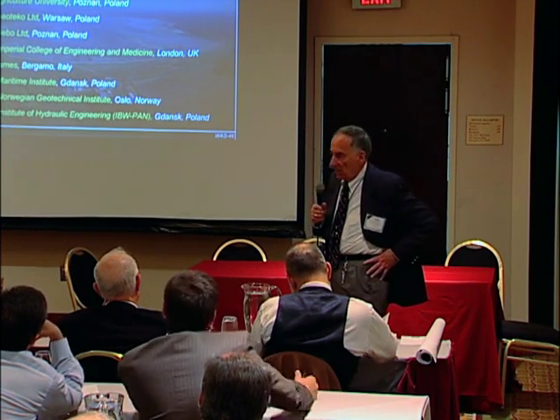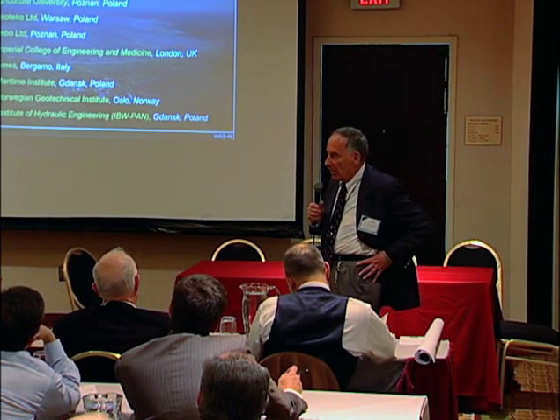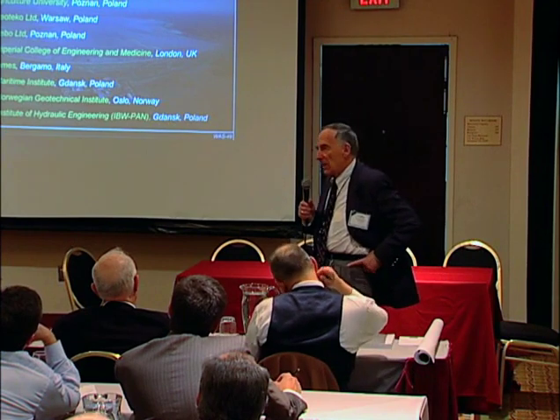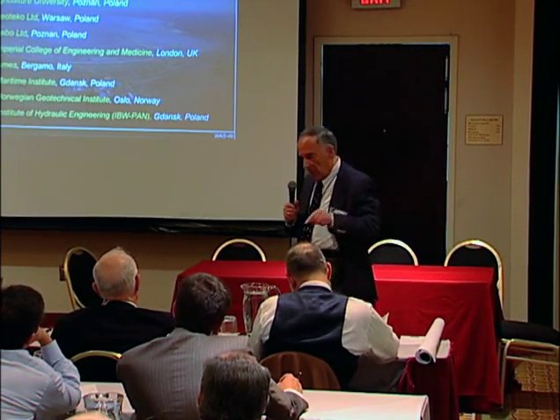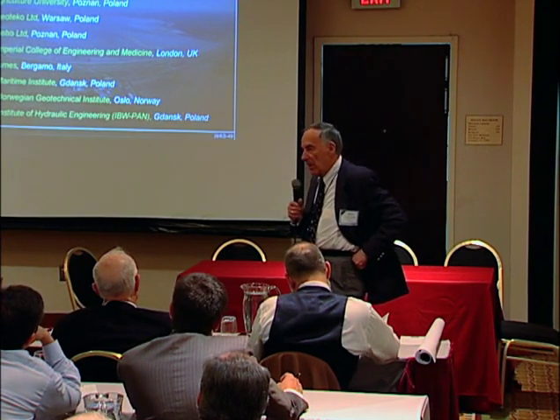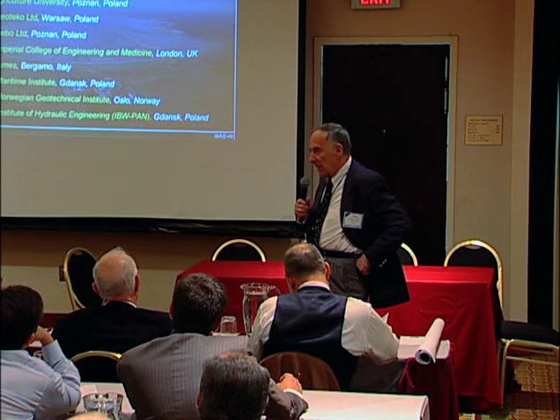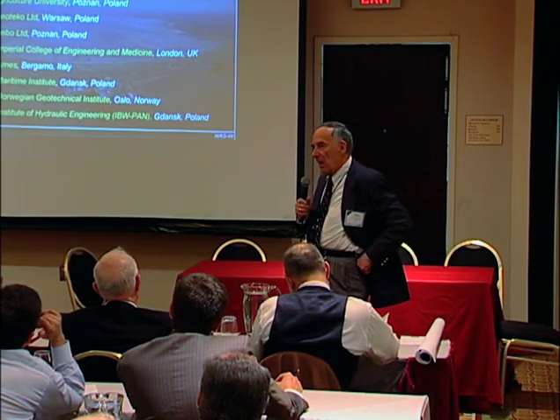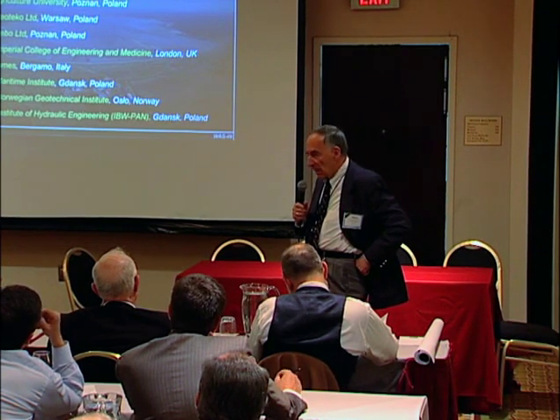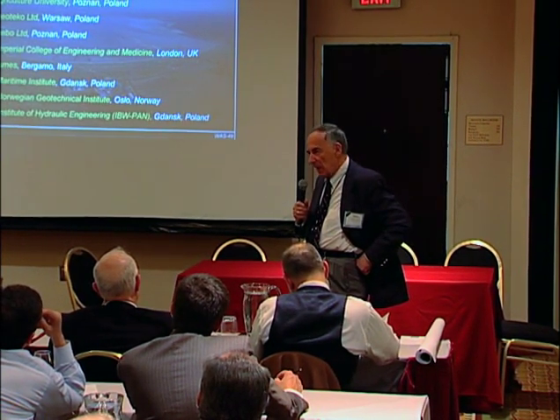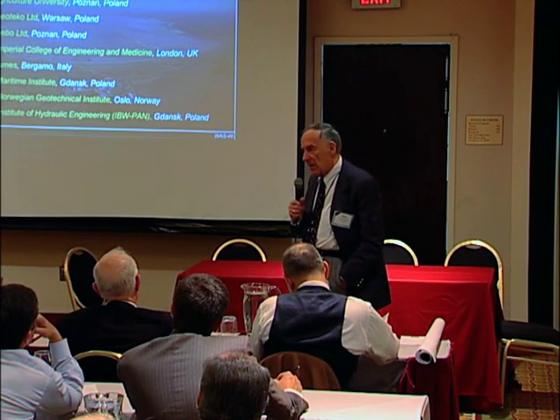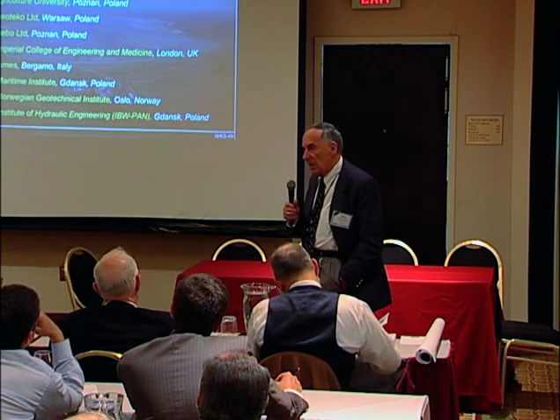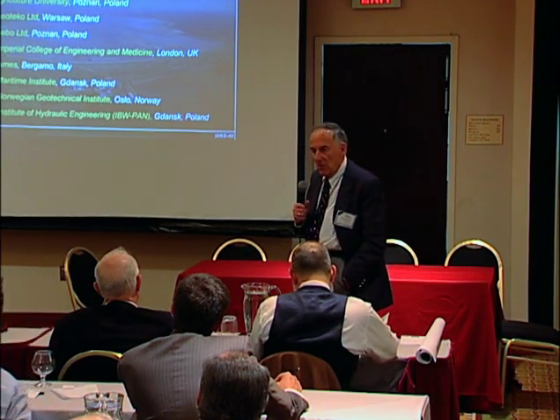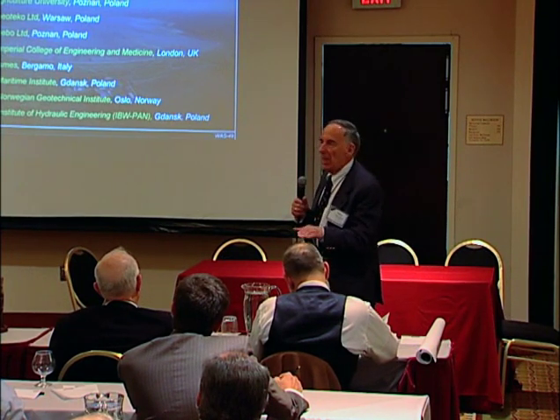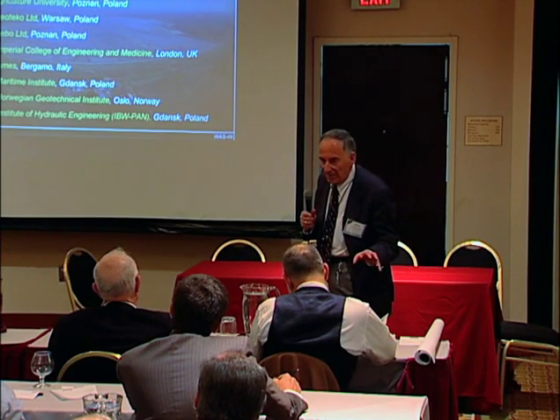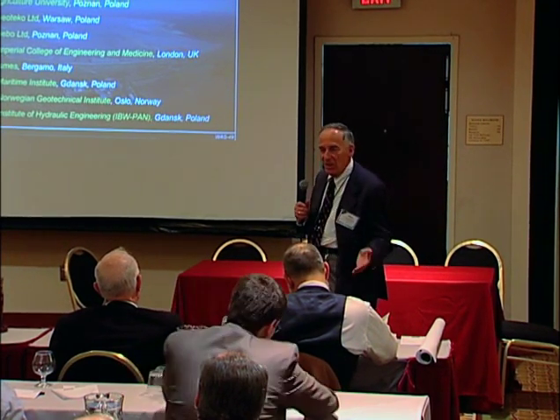On the other hand, we have some indication from the shear wave velocity and from some general information that tailings, indeed deeper tailings, are subject to aging. And in fact, our next step will be to retrieve the undisturbed samples and to investigate in a K0 consolidated specimen in a large 4-inch diameter triaxial cell the aging, for a long duration test. I expect that it will be quite important aging, certainly much higher than we expect for clean quartz sand, which still is not negligible according to the Mesri data. Okay.